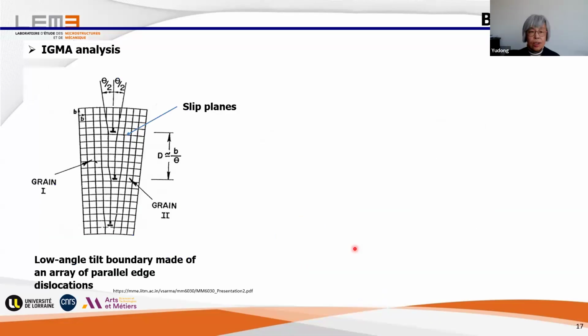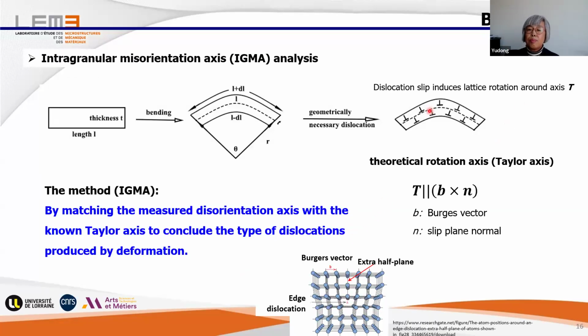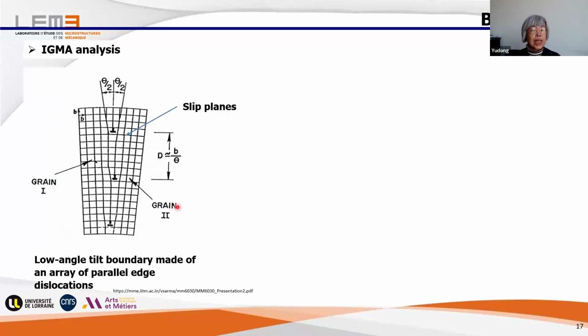Okay. So if these dislocations in the previous configuration have high energy, then with the thermal effect they will reduce the energy, and the dislocations will climb and form a kind of low angle boundary. The existence of such a low angle boundary also makes these two parts disoriented, and so we can also describe this with an angle and axis. And this axis is also the Taylor axis.